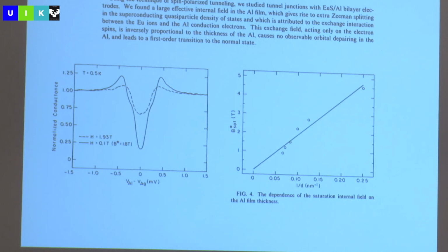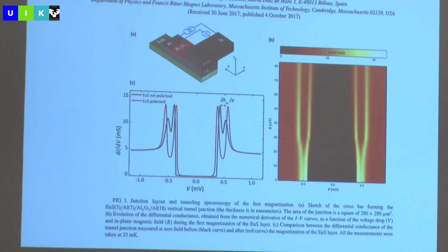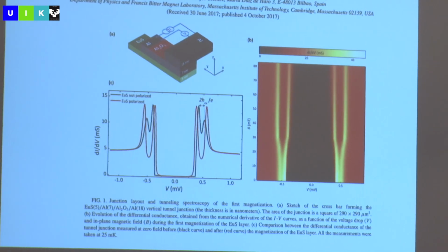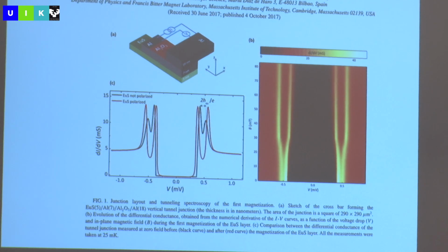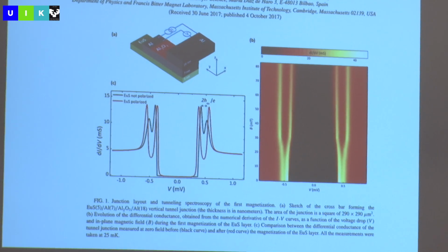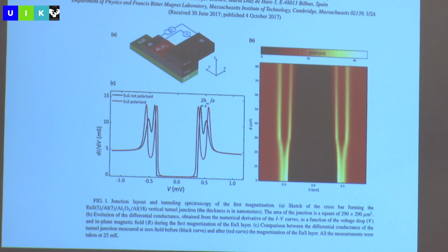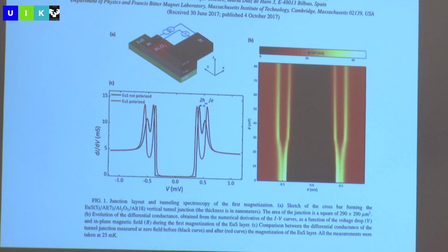I found it remarkable that you're putting an insulator on the surface of a superconductor, and just because that insulator is magnetized, the superconducting density of states in the superconductor splits as if it's sitting in 4 Tesla. I personally don't find that particularly intuitive. I only want to mention that this field has continued to advance and that there's a whole literature on it, all the way through, in this case, 2017 in Physical Review Materials. And you can learn about it, and if you want these slides.